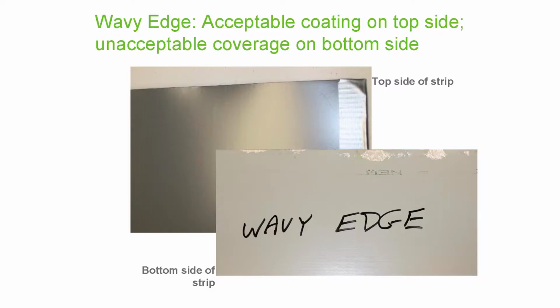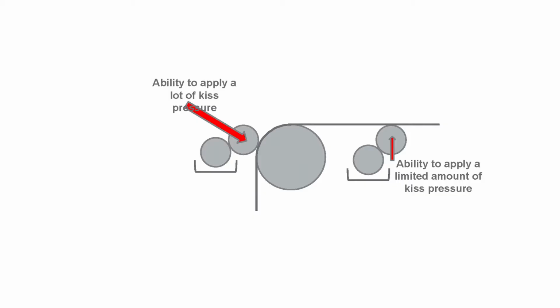When you press that applicator roll onto the web, and in many cases you're pressing it right up against the backup roll, that's okay. If you've got a wavy edge, this has been taped just for protection. When you have a wavy edge like this, you can overcome a lot of that problem because you're pushing so hard. But if you've got the backside, so this is the backside of this panel, there's only so much tension that you can push up, right? There's only so much that you can push against that web. So it just creates gaps on the backside.